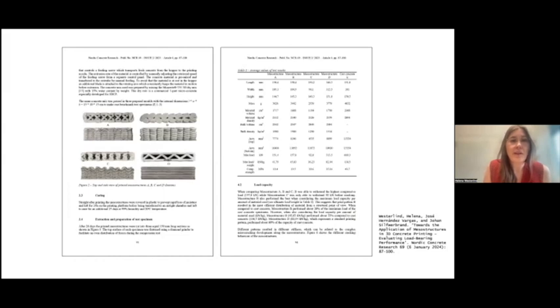So in this study, we looked at three non-standard patterns and a more conventional pattern using 3D printing, the truss or triangle infill pattern, and tested them to maximum breaking point. And unsurprisingly, we found that patterns A, B, and C do not perform as well as the standard pattern because they are not overlapping in each layer, reducing the points of contact. But interestingly, it is possible to affect the bulk density of concrete through the generation of these patterns.